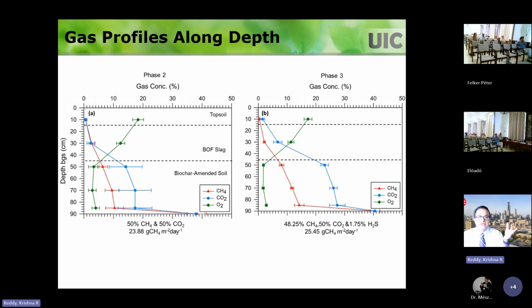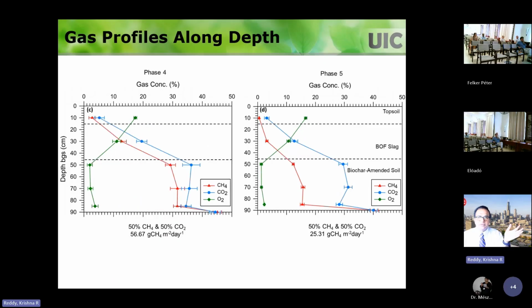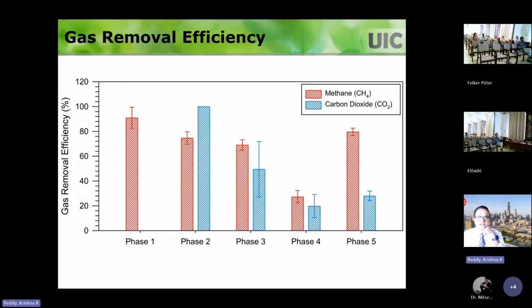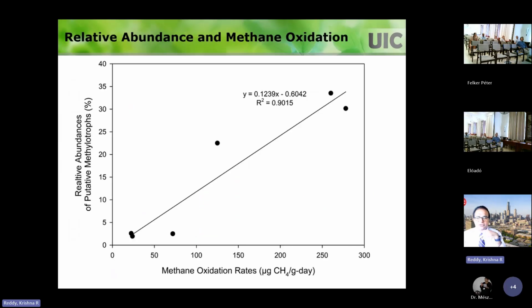So to make it simple, whatever we found in the batch and column experiments were confirmed in this large scale experiment. So in different phases, we could see the methane removal and carbon dioxide removal and so forth. And we also did the microbial characterization, and we found out that type 2 methanotroph was dominant in many of these column experiments.